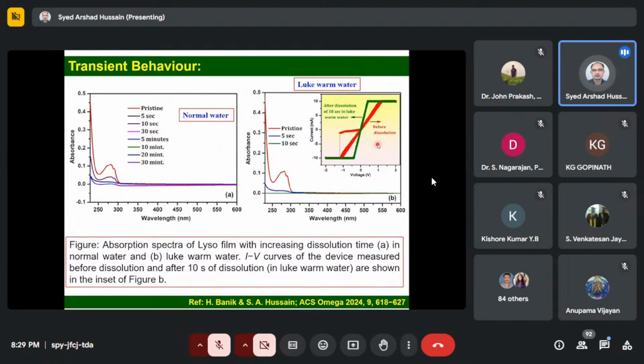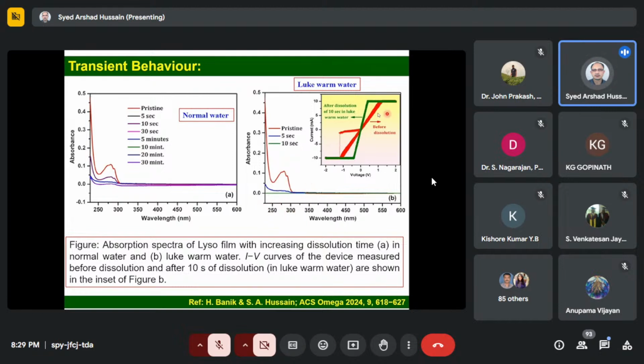We have demonstrated that our device can be dissolved in lukewarm water within a fraction of seconds. In say 10 seconds, you can see we measure the absorption of the device once it's just put in the lukewarm water. After 5 seconds, this blue one. After 10 seconds, you see it's flat. So there is no active device material. And also we studied the IV curve. You see this green, initially the red curve, you see these two states were there. But when we dip it in lukewarm water for 10 seconds, then take it out, then measure the IV curve, we see that it shows a linear IV curve. This is due to ITO. It's conducting, so it's showing ohmic nature. So it shows transient nature.